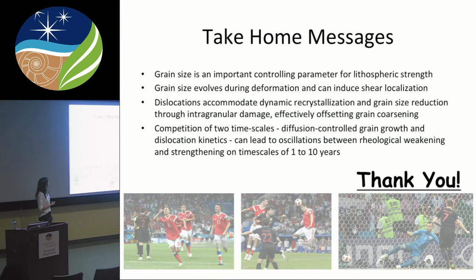But more importantly, maybe, I hope I managed to convince you, although I didn't go into the details of rheology. Grain size is an important parameter that controls the lithospheric strength. It evolves, so grain size can change during deformation and can lead to important feedback between how the material is deforming, how the grain size is evolving, and the rate of deformation will depend on grain size, and grain size itself will depend on the rate of deformation because that's the work that it needs in order to change the grain size.